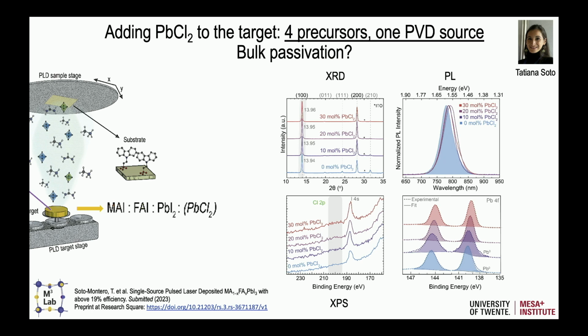We do the same steps, mechanosynthesis with some lead chloride at different amounts, 10%, 20, or 30% lead chloride. And what we see is if we add lead chloride, the structural properties are actually the same. So we keep the same orientation, not much shift. In XPS, it was not possible to see any of the chloride, so we still have kind of an open question on that. There are a lot of hypotheses, like the lead chloride leaves, or the chloride leaves the sample. We still have to prove that.